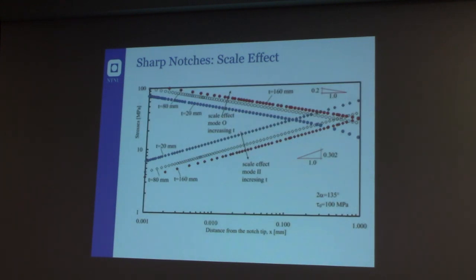This is the stress field along the bisector line. So the scale effect of mode O, if you increase the size of the component, is also increasing the stress field. If you increase the size of the components, you are decreasing the effect of mode 2. It's a bit difficult, but you can understand it if you make a finite element model very easily. I only want to show that the advantage of a linear elastic approach is that you can use the superposition principle and that the scale effect is always verified. This is the most important consideration that I want to underline.